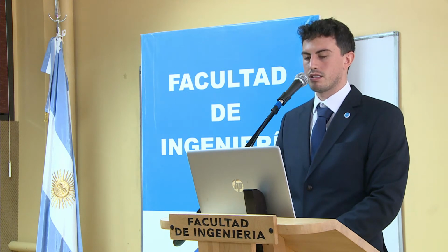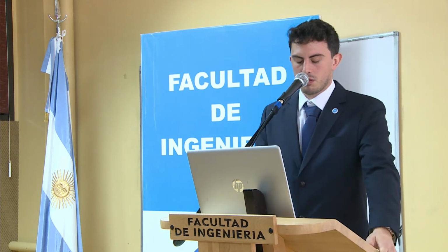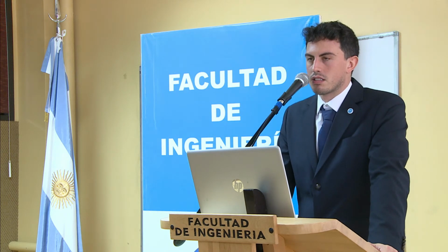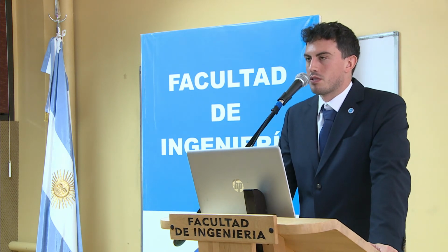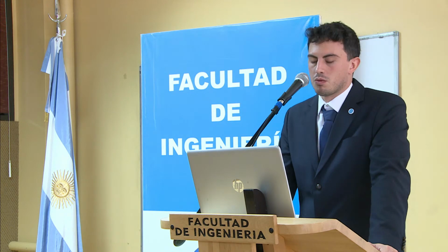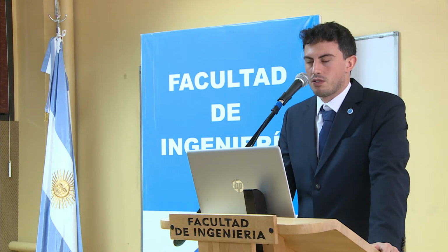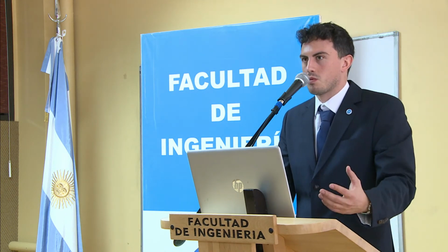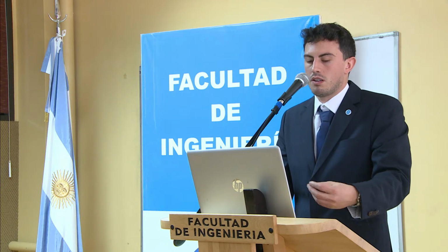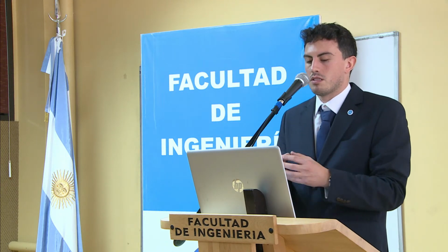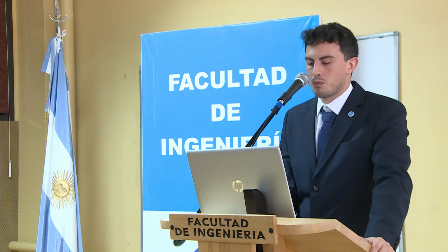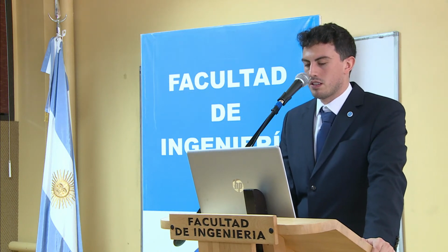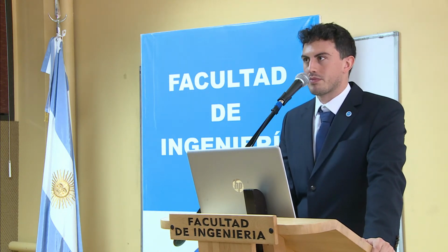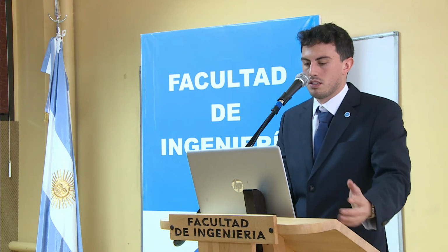In this case, the total porosity was determined by oven drying. So we just took a sample from the cement and we took the weights before and after heating. That was total porosity, and we don't know if inside the sample there is a bubble. But we found that the values were really consistent, around 40% in this case.